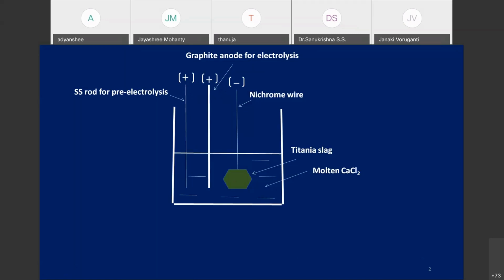It should be below the decomposition potential of the electrolyte, like calcium chloride. You cannot decompose the electrolyte because you don't disturb the electrolyte. Otherwise, the electrolysis will be hampered. So in this process, the electrolysis is carried out much below the decomposition potential of CaCl2, that is 3.2 volt. So we are carrying out the electrolysis at a potential of 3 to 3.1, which is below the decomposition potential of CaCl2.